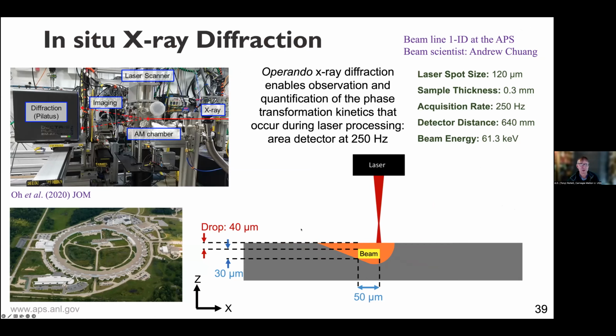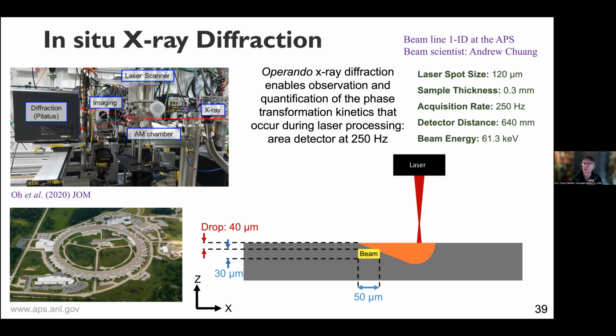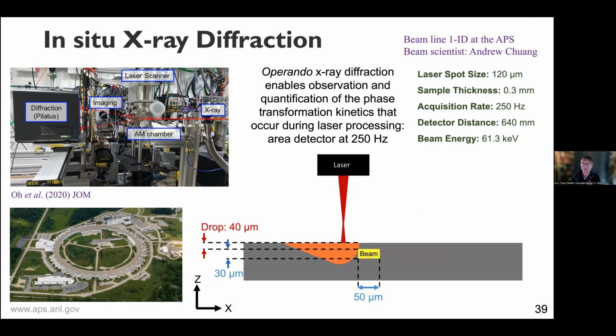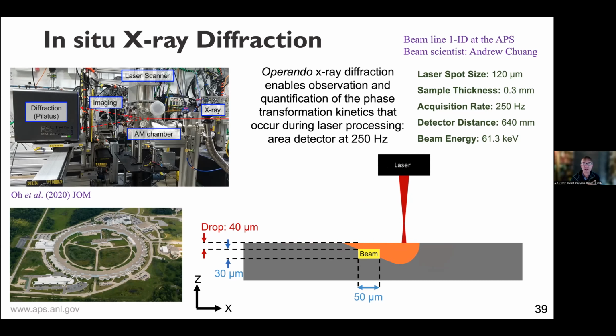So first of all, the cartoon gives you a slightly clearer picture of what it is that we're looking at with a beam. But now I'm going back to 1ID. I owe considerable debt to Andrew Chuang as the beam scientist who's helped us with this. And it was people like Kamel Fazar at 32 and Tao Sun before he left. So here we're back to using a monochromatic X-ray beam. We have a very nice detector, we typically call it the Pilatus, which has a large area detector.